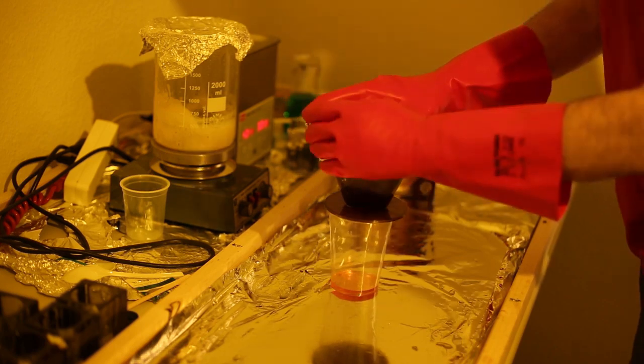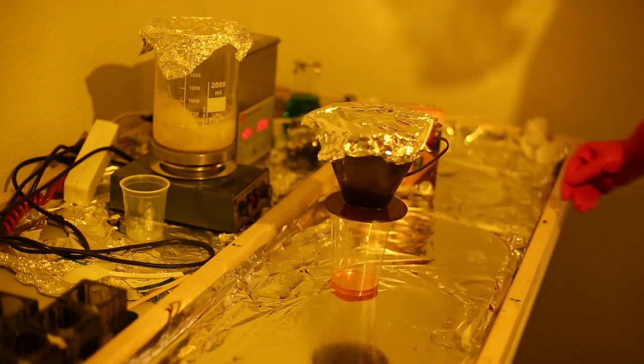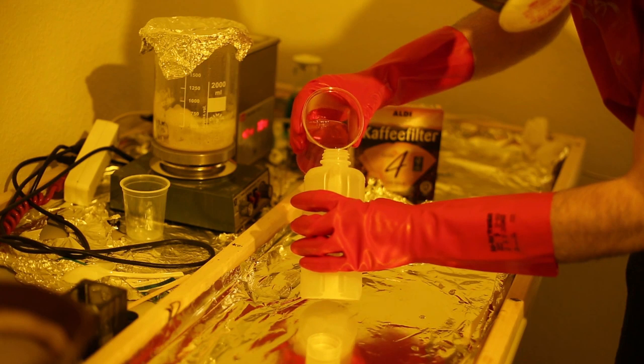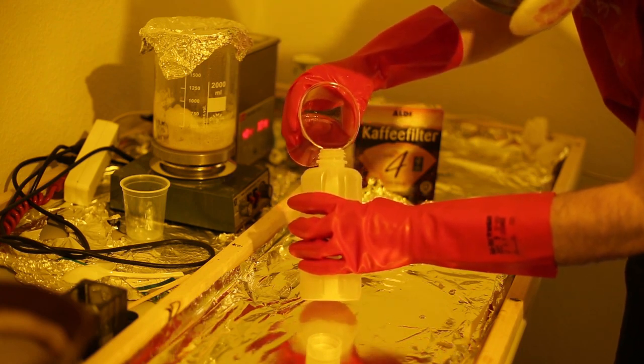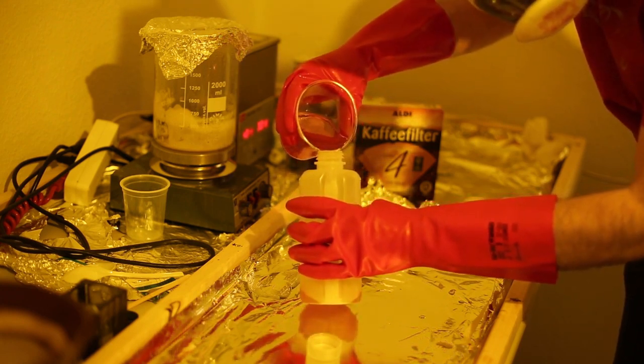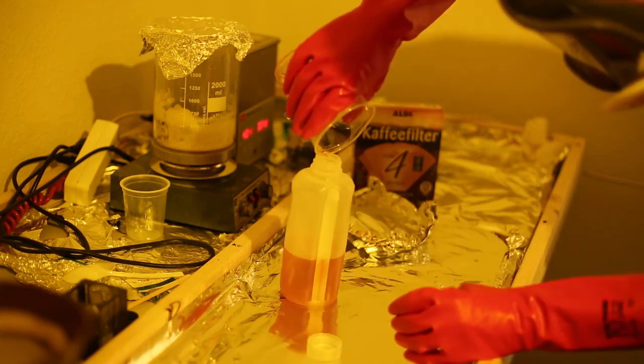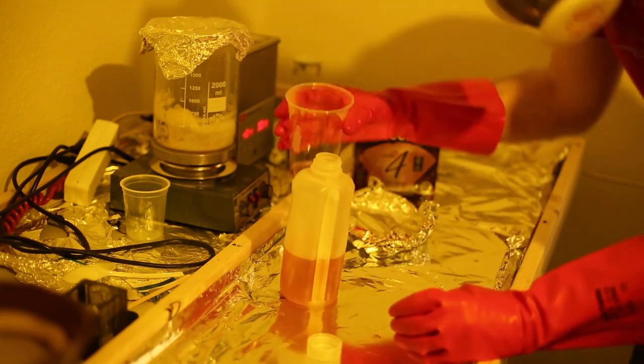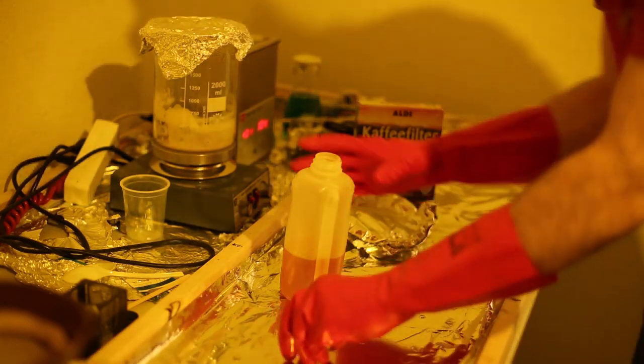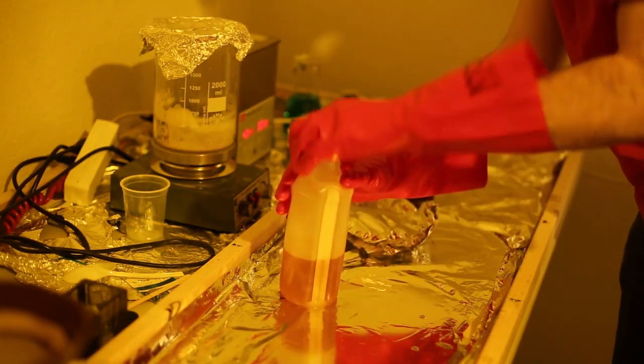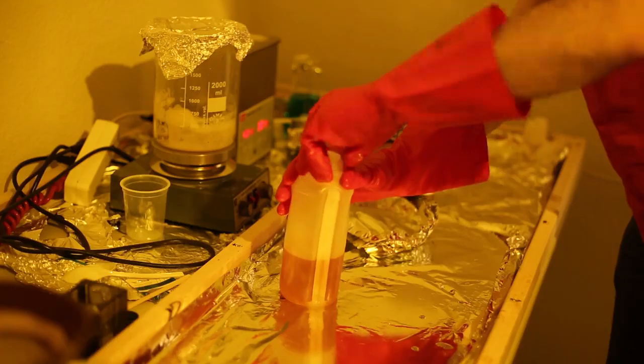From the transparent cup, the filtered gelatin is poured into a special coating bottle. It's a squeeze bottle that can hold about 400 milliliters of gelatin. It has a spout at the top, which is connected by a tube to the bottom of the bottle. When you squeeze it, the bubble-free gelatin from the bottom of the bottle gets forced out first.